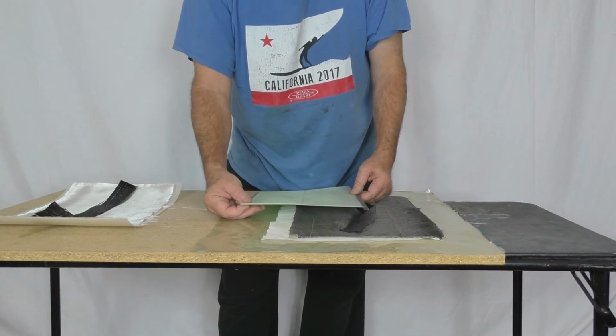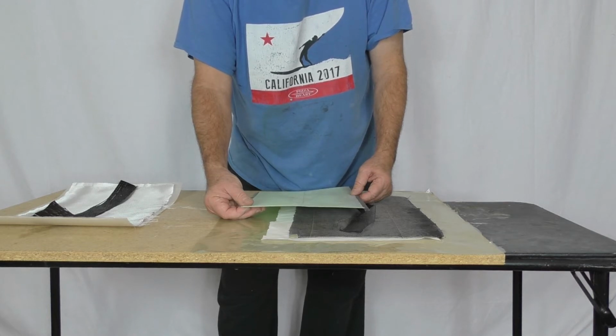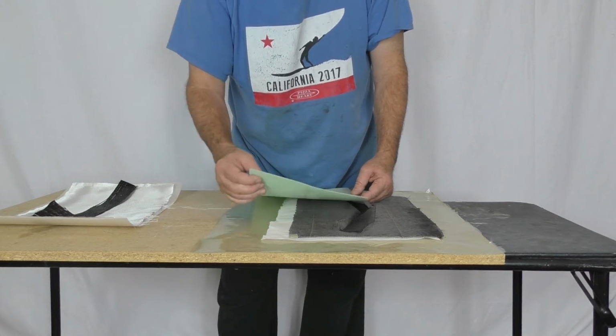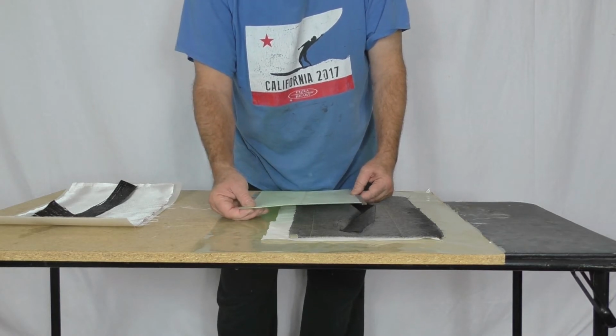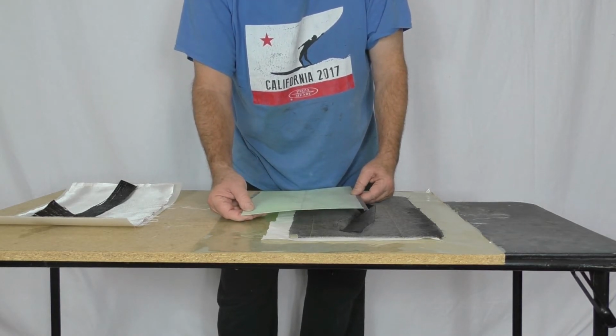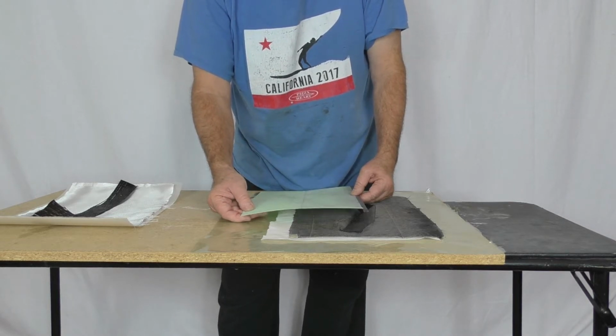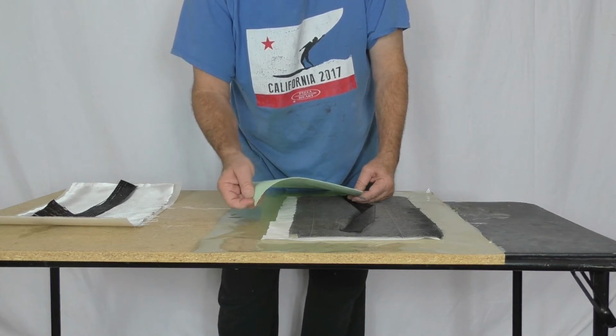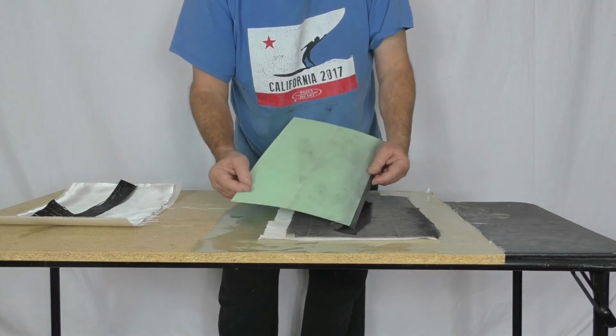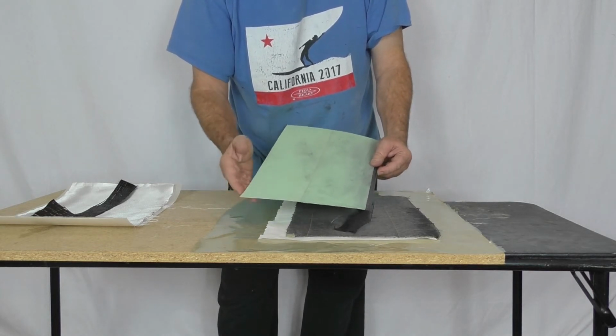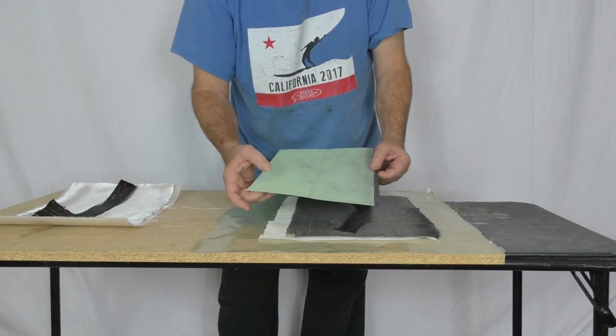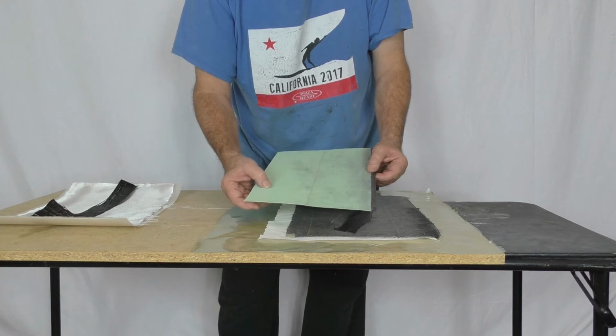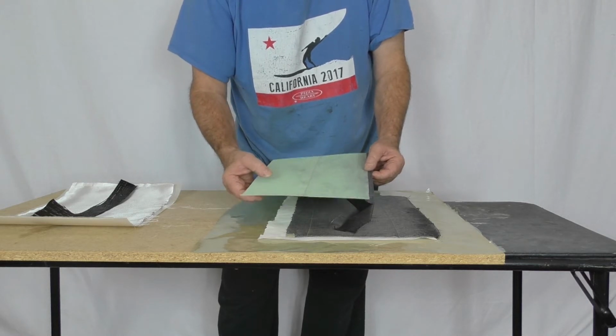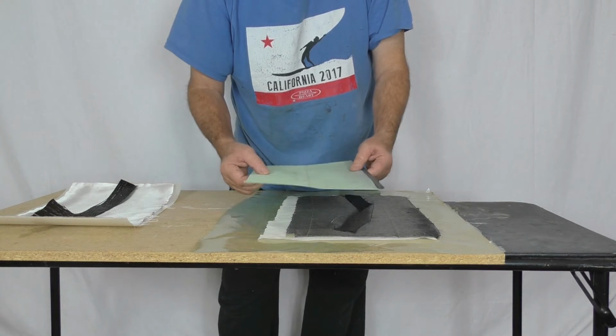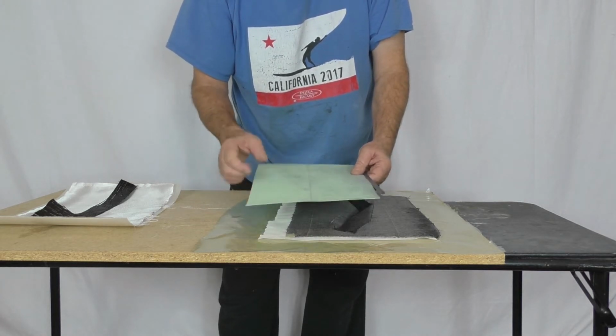This is Airex foam. It is also PVC. Divinycell is a PVC. This is a PVC made in Europe. This particular material is 1.2 millimeters thick, about a 1/16 of an inch thick. And it has several advantages over Divinycell. It is more flexible without cracking. It has a finer cell structure in the foam so that when you wet out the cloth, you don't get as much resin transferring into the foam where it's not doing much good, just adding weight. And it is very durable. It's crack resistant, impact resistant.